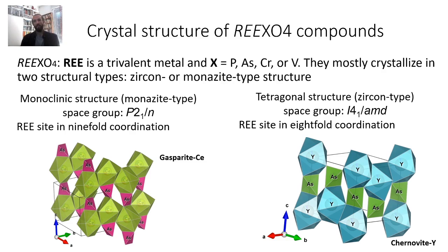Besides symmetry, a primary difference between monazite and the zircon or xenotime type structure is the coordination environment of the RE cation. In the monoclinic monazite structure, the larger light RE ion is coordinated to 9 oxygen atoms, whereas in the tetragonal structure of xenotime and chernovite, the smaller heavy RE, yttrium or scandium are 8-coordinated with the oxygen ions.